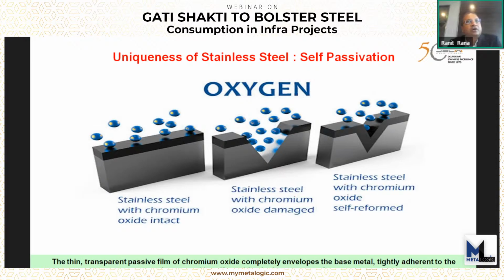Stainless steel, on the other hand, because of its innate chemistry, the chromium reacts with the oxygen to form chromium oxide. And chromium oxide lends the corrosion resistance. And even when the film gets broken, the chromium in the metal immediately reacts with the oxygen to reform this film. And that is the reason why the longevity of structures with stainless steel is significantly higher as compared to any other coated steel.